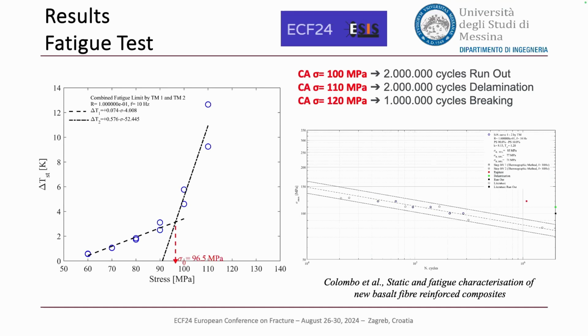Here I combined the results related to the stepwise fatigue test and the thermographic method, which provides a fatigue limit of 96.5 megapascal. In support of the stepwise fatigue test, we have also done a constant amplitude fatigue test that provides a runout at 100 megapascal, which is near the fatigue limit obtained with the thermographic method, a delamination of the specimen at 110 megapascal, and the breaking at 120 megapascal after 1 million cycles.